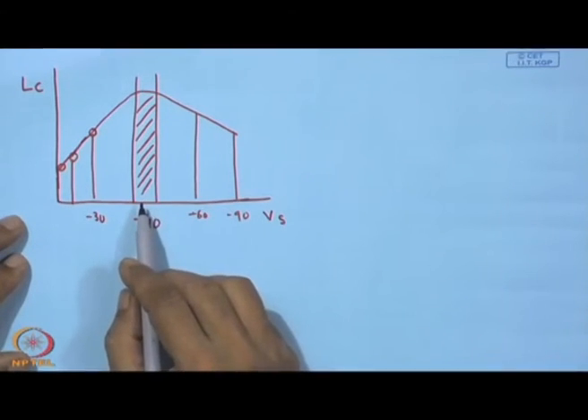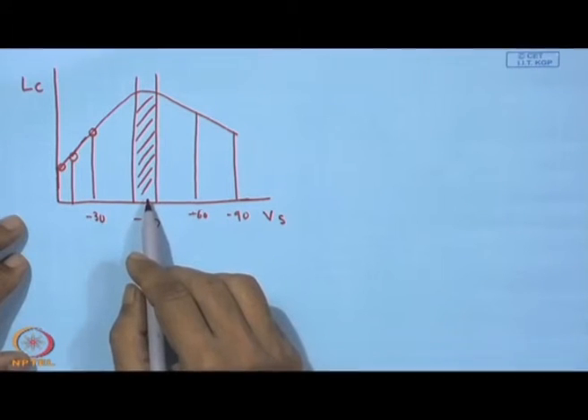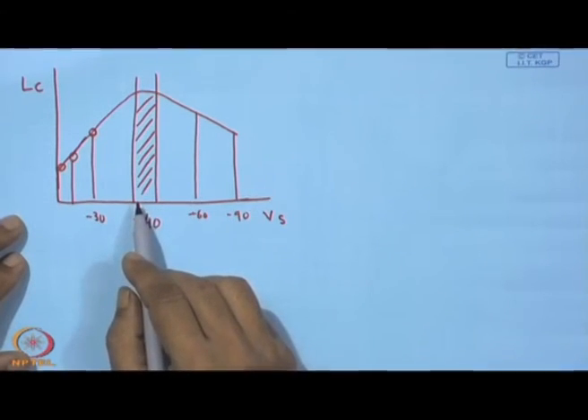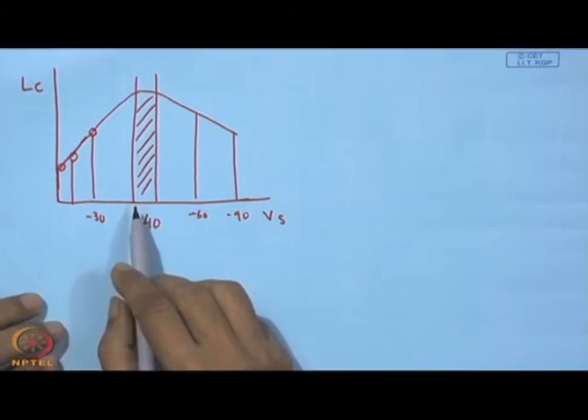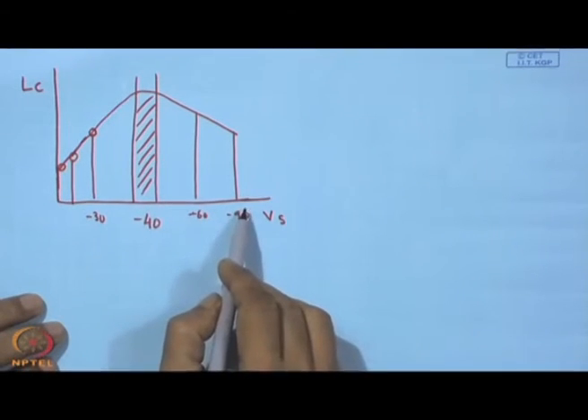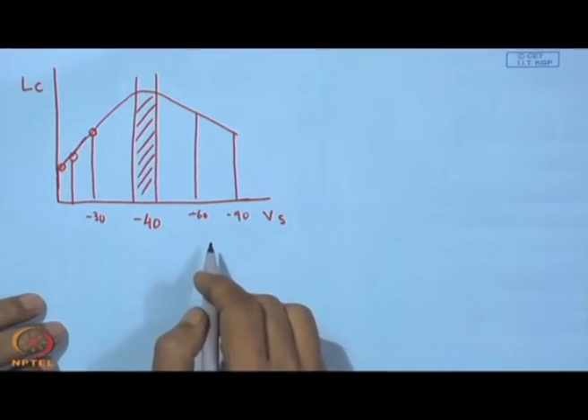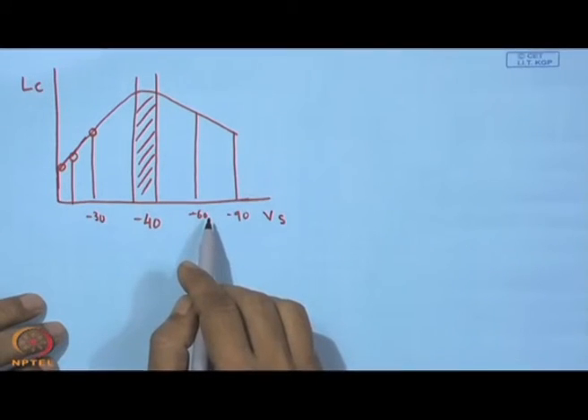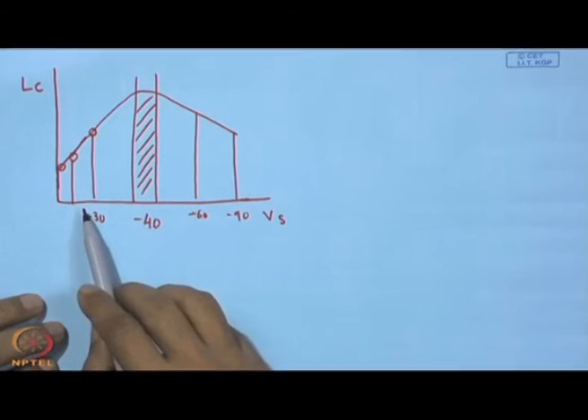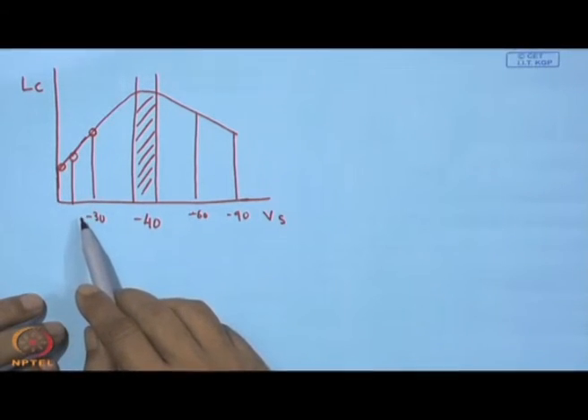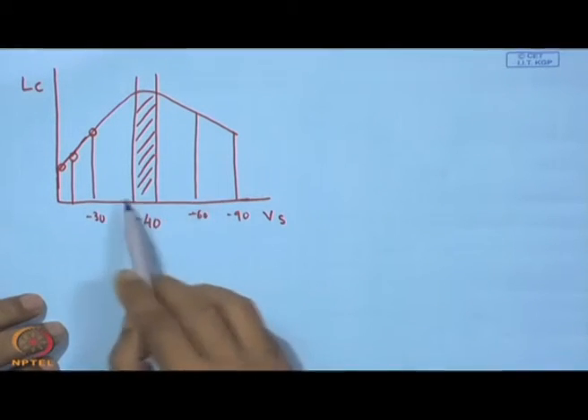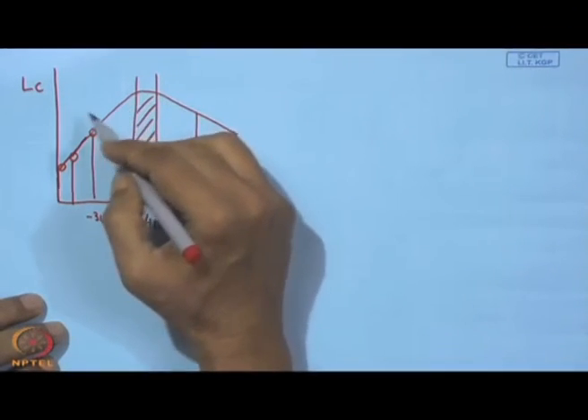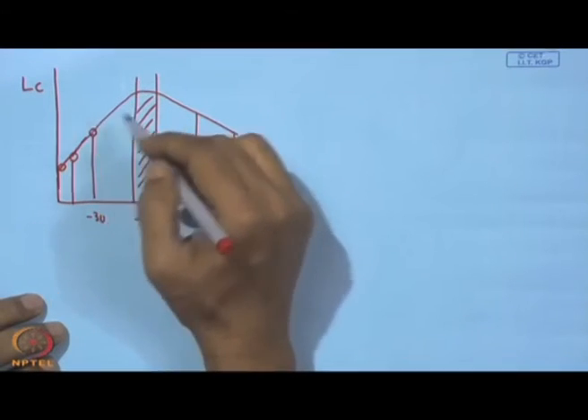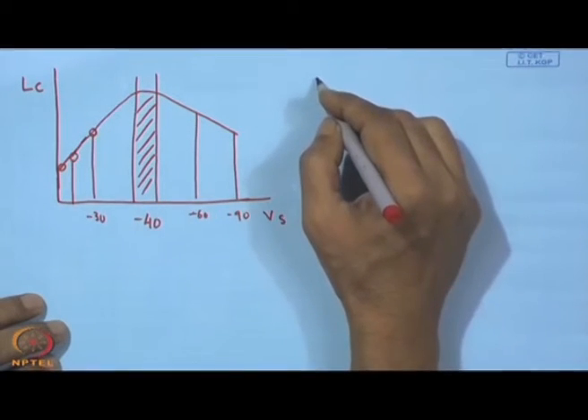So, what happens in this case? Too much stressing at the interface, and also, because of very high energy availability, too much diffusion or a thick diffusion layer, and on this side there is no diffusion. So, no diffusion or too much diffusion, both are counterproductive. So, a value in between could give one of the very best results so far as adhesion is concerned.